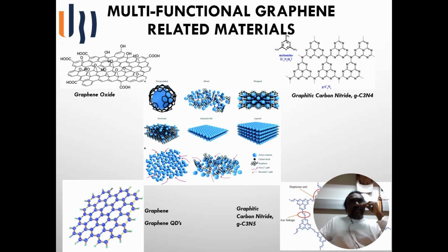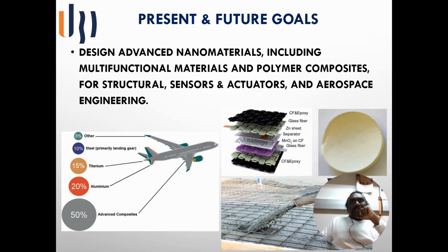And presently, at C-MAST, we are developing graphene-related materials like graphitic carbon nitride and graphene oxide, and functionalization of the graphene oxide with epoxy groups. These nanomaterials are incorporated into the epoxy resin in order to make structural and multifunctional nanocomposites for aeronautic applications. Here you can see the aerogel prepared with graphitic carbon nitride. As you can see, the color is yellow, because this color comes from the graphitic carbon nitride.